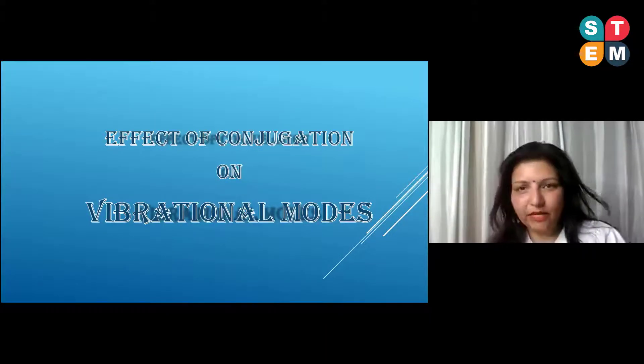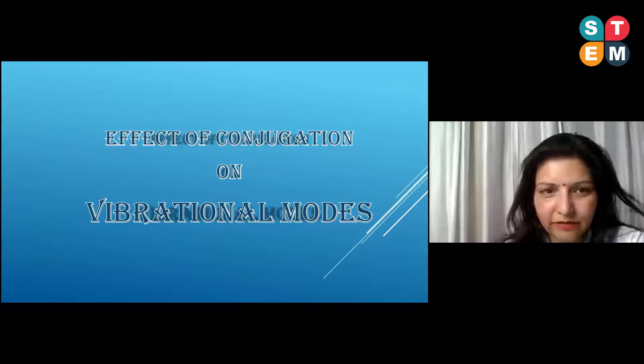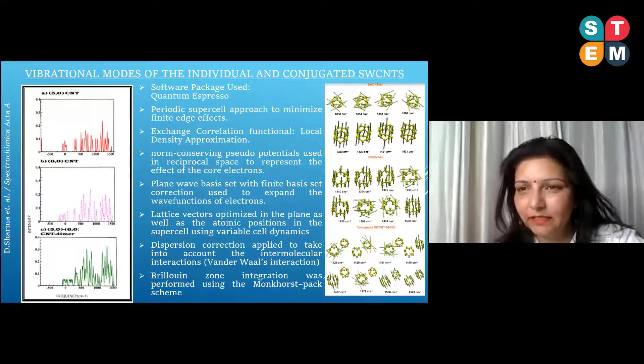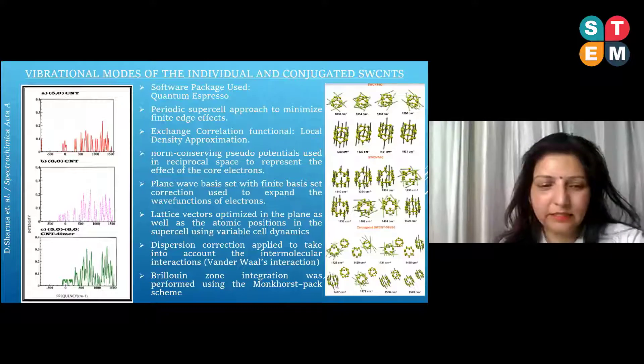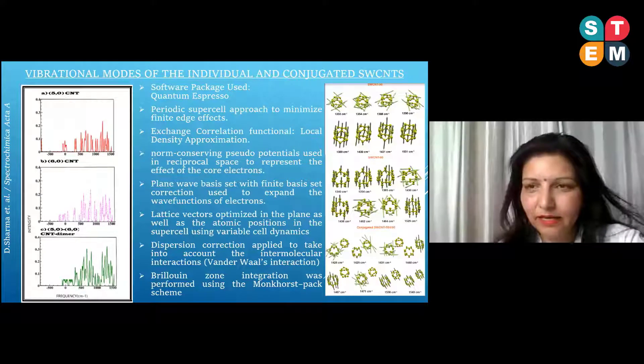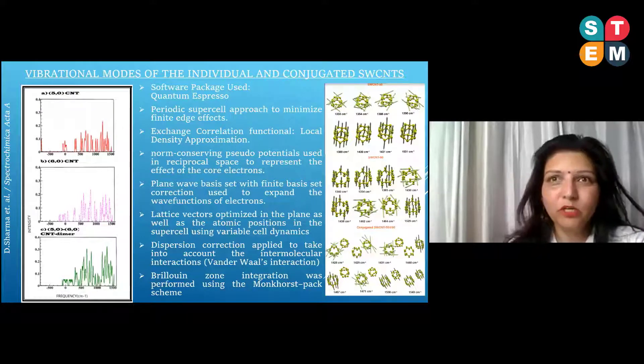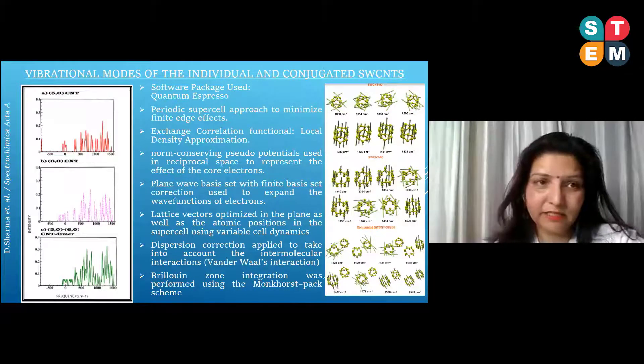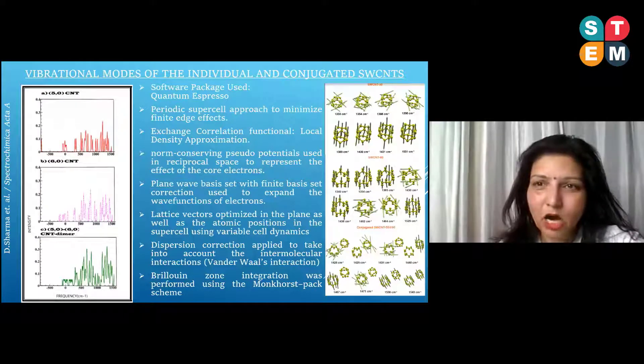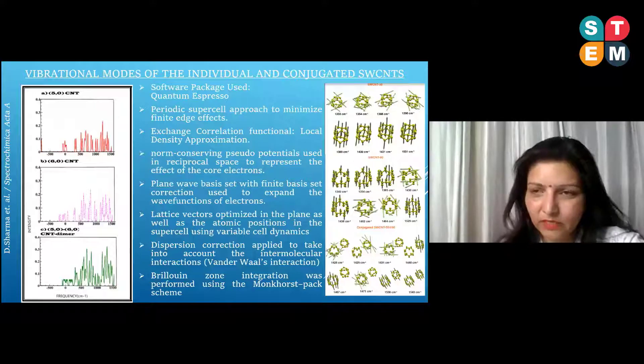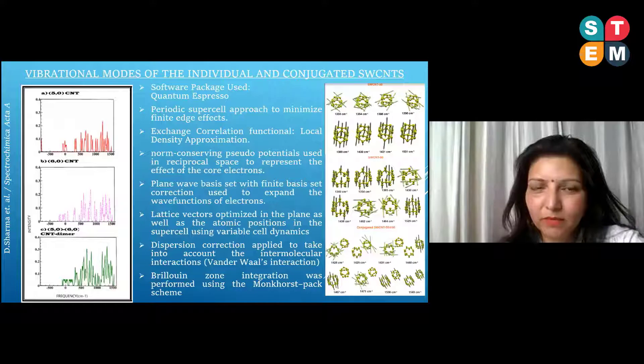Another study I would like to share is the effect of conjugation on vibrational modes. I found a paper reporting that a single-walled carbon nanotube dimer has been discovered, in which two single-walled carbon nanotubes are held by van der Waals forces, parallel to each other, forming a heterogeneous dimer. Motivated by that experimental paper, I simulated a dimer comprising a 5,0 CNT and a 6,0 CNT to study how conjugation alters the vibrational modes. This study was done using the Quantum Espresso software package with a periodic supercell approach to minimize finite edge effects.